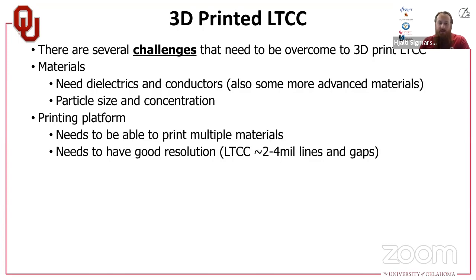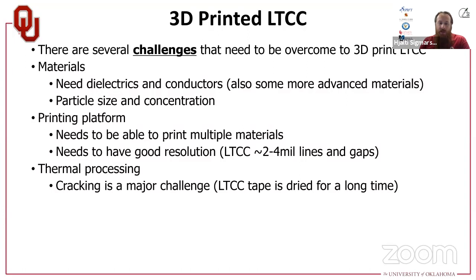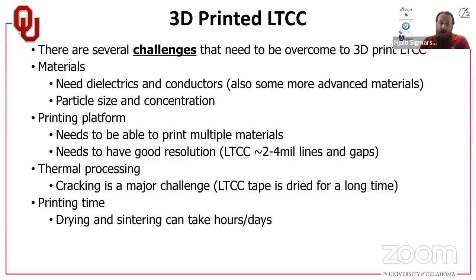Well, we have a lot of other platforms, and I'll talk about that in a little bit. One of the major challenges of doing 3D printed ceramics, and this goes a little bit to our first speaker's discussion on drying and sintering, is cracking. Cracking is a major challenge for 3D printed ceramics and sintered ceramics. And as an example, for comparison, in traditional processing of LTCC, the tape itself is dried in very well-controlled conditions for a very long time, and there's a reason for that. And the sintering process is also relatively slow. Drying and sintering can take a lot of time.